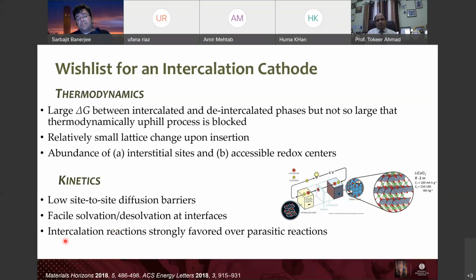And then the other thing I sort of briefly alluded to before. So you've got this whole series of intercalation reactions happening, right? So the intercalation reactions require that the diffusion of ions through the lattice does not have a large barrier, so the ions can readily move through the inside of the lattice. They also require very easy solvation at the surfaces, right? But these two reactions have to be easier than parasitic reactions. So a parasitic reaction